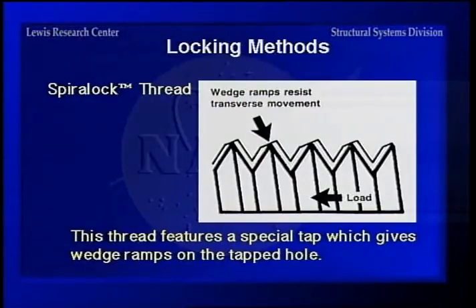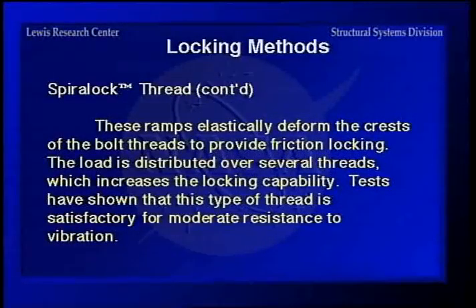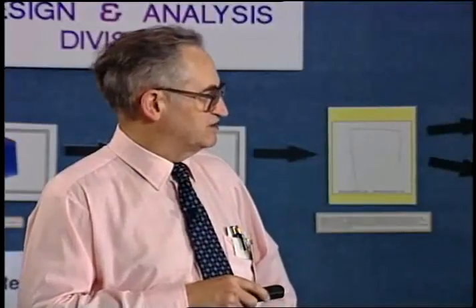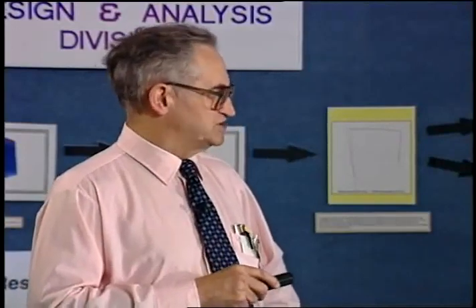Here is another type of thread that's a special thread, Spiralock. I think Detroit Tap and Die is the holder of the patent on this one. And this is a cross-section here of a tapped thread and a fastener. Now, the problem when you install it is you have to have Spiralock's tap because this is an oddball. See, the tapped hole does not fit the thread, and you get your locking action by actually wedging the ramp of the thread up against the oddball type tap. But you can distribute the load over several threads, so it offers better locking capability than an ordinary thread would. And some people have used it and run vibration tests, and it holds up fairly well.